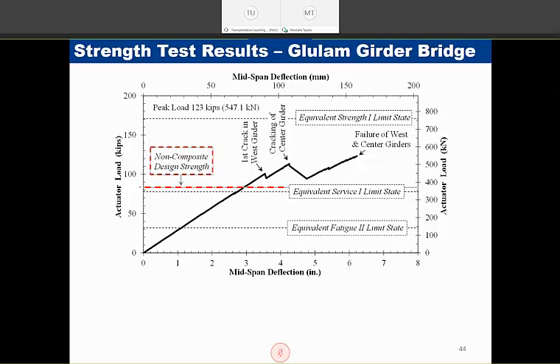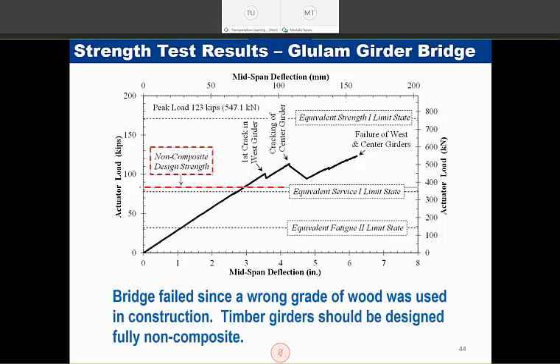Here the force deflection response of the glue lam girder bridge is shown. The bridge did not meet the equivalent strength limit state because the as-built girder material was weaker than the specified material due to the construction error that I had mentioned. And the bridge girders were designed assuming a partial composite action. So we calculated this red line. We calculated the bridge strength using the correct assumptions, as I just discussed, and we were able to estimate the capacity of the bridge with the safety margin. So our recommendation is, if you want to use this bridge, make sure that there is no composite action, design the bridge for that, and make sure that the constructor or the builder is using the strengths of the material that you specified.